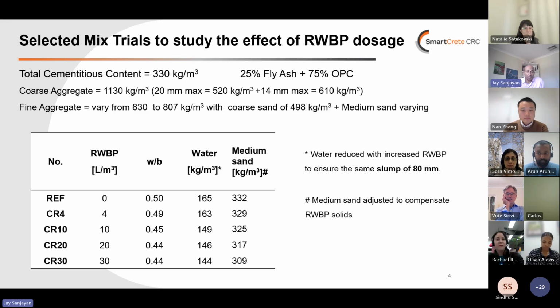And the fine aggregate we need to change between the mixes, because the water-based paint has, for example, you take 10 liters of water-based paint, that's the third mix, and out of the 10 liters, there's about 7 kilos of solids. So we take off the 7 kilos from the sand, the medium-sized sand, and then the rest we take off from the water.